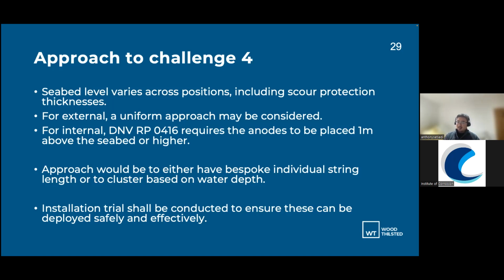But because of that, across 50 to 100 locations, the seabed varies. We have to adjust our string, and we have to look at how the CP model correlates between the deeper cluster and the shallower clusters. So that's what we have here. Our approach is to have bespoke individual strings or clusters, and especially for galvanic anodes, the anodes are heavy, so installation trials will need to be conducted to make sure that they can actually be deployed safely.